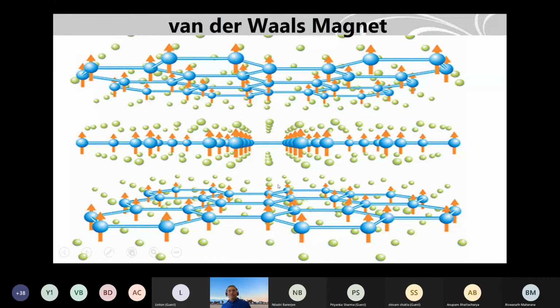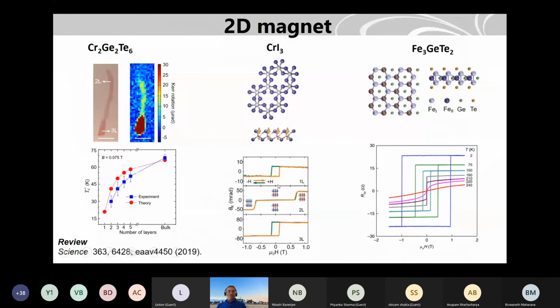These magnets were discovered around 2017, and lots of activity is going on here. This is just from a review article I took, showing that there are different types of 2D magnets: chromium germanium telluride, chromium iodide, iron germanium telluride. What you see here is an insulator, so you have to do some Kerr microscope experiments. This is the Kerr rotation signal here, and how the Tc changes with number of layers.